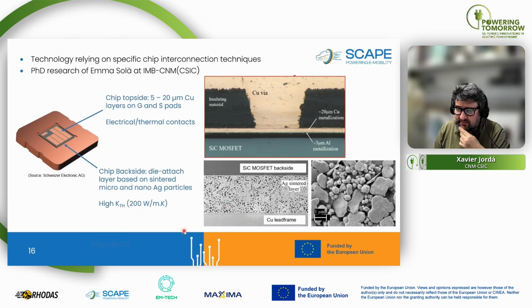In particular, at thermal level, the thermal conductivity of this die attach material achieves up to 200 watt per meter Kelvin, while, for example, typical soldering materials achieve values between, let's say, 20 and 50 watt per meter Kelvin. Then it has been very, very interesting using this material. And let me also mention that the development of these technological solutions has been developed in the framework of Emma Solà's PhD research here at IMB-CNM again.